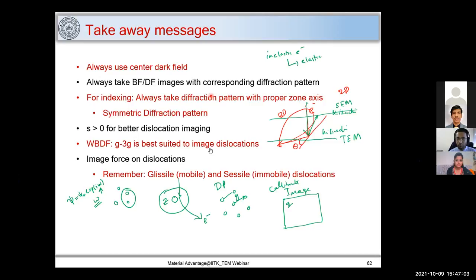Okay. So there is no such value for alpha and beta tilt. In my PhD days I also thought I could calculate some alpha and beta tilt values, but that is a myth. So you try to go to the zone axis and try to tilt it. If you are very close to the zone axis, you can find out what alpha and beta are.